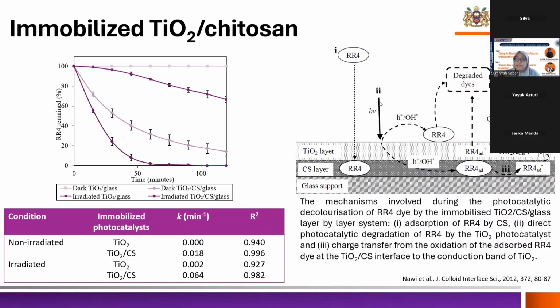And then the second one is the direct photocatalytic degradation of the dye by the titanium dioxide. So it's only on the surface of the photocatalyst where the dye is being degraded. And the third one, we observe that the adsorbed dye in the chitosan layer also participates in the reaction by involving the charge transfer from the oxidation of the adsorbed dye at the titanium-chitosan interface, where the charge is being transferred into the conduction band of TiO2. So it further enhances the degradation of the dye.